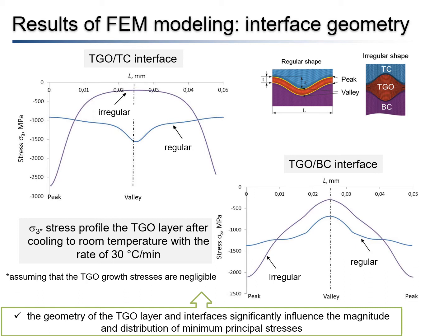You can see the distribution of the minimum principal stress calculated for the regular and irregular thickness of thermally grown oxide. For example, in the case of irregular shape, the compressive stress reaches the value of about 2700 megapascals at the peak for TGO-TC interface, which is almost 3 times higher in absolute value than the stresses developed at the same location in the thermal barrier coating system with the regular TGO layer geometry. A similar effect was observed in the peak area of the thermally grown oxide-bond coat interface.